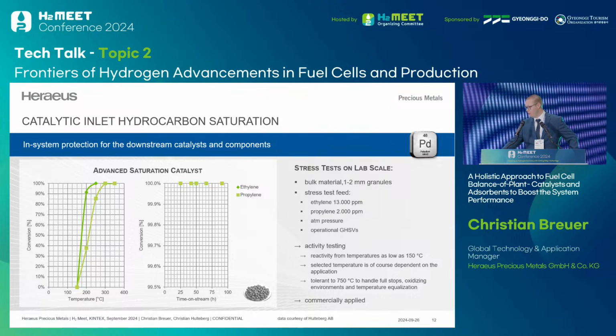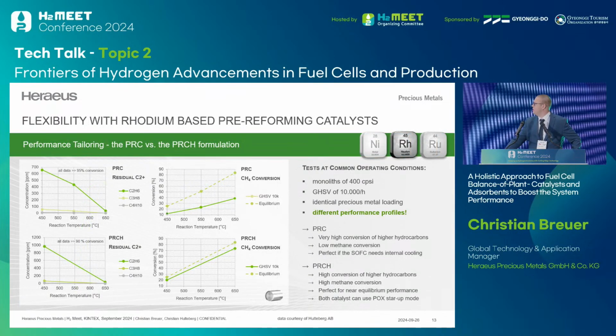So we use these saturation catalysts and basically protect the whole downstream system by converting them to saturated hydrocarbons. And this brings us directly to the next system, the main reforming catalyst, or the pre-reforming catalyst in this case. You see, for pre-reforming catalysts we have very different options. We have nickel-based options, we have ruthenium-based options, which I know are quite popular here. But we also have rhodium-based options.